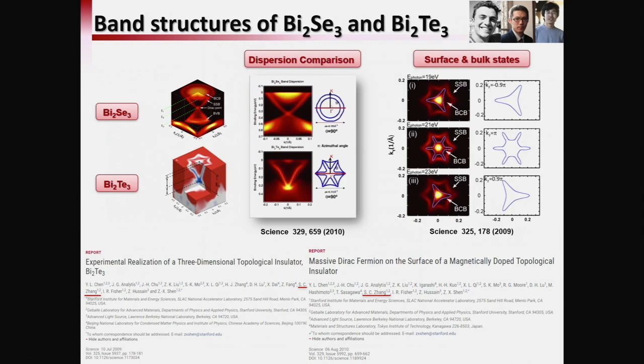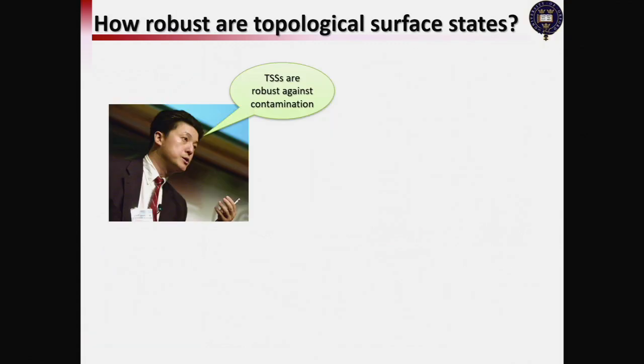And then only a month later, we got pretty nice data from bismuth telluride and later on bismuth selenide. These are the first two three-dimensional topological insulators we measured, and we got the band structure, which clearly shows the in-gap topological surface state. These are the first two works we collaborated on with Shoucheng. That was a very good memory. Of course, other collaborators include Jimmy Analytis, now at Berkeley, Jinghao Chu, now at U Washington, and Xiaoliang Qi, who is present.